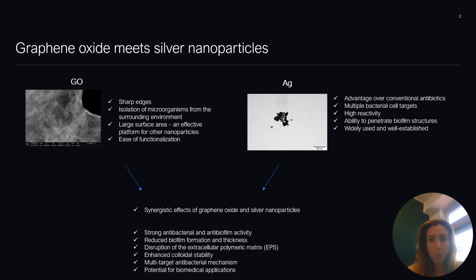Before discussing the developed nanocomposite, it is important to highlight that both graphene oxide and silver nanoparticles possess unique properties that contribute to their antibacterial activity. Graphene oxide exhibits several characteristics that make it an attractive antimicrobial material. Its sharp edges can mechanically damage bacterial cell walls and membranes, while its ability to isolate microorganisms from the surrounding environment may interfere with nutrient exchange. In addition, graphene oxide provides a large surface area, making it an effective platform for immobilization of other nanoparticles, such as silver nanoparticles, and it offers a high ease of functionalization, enabling the design of multifunctional materials.